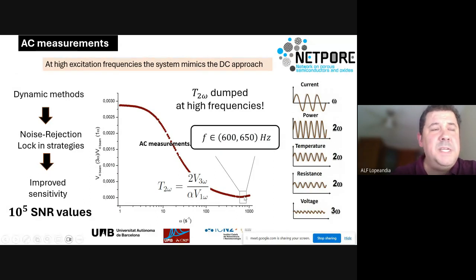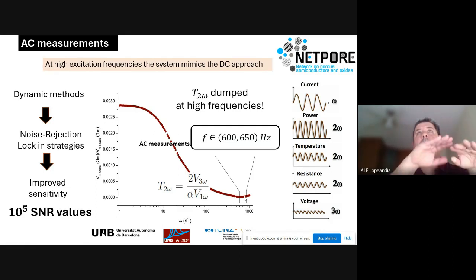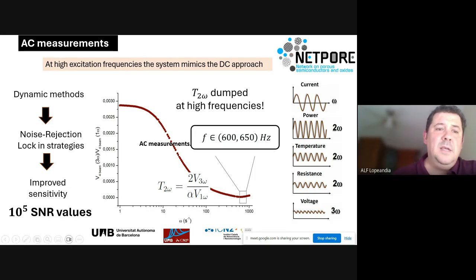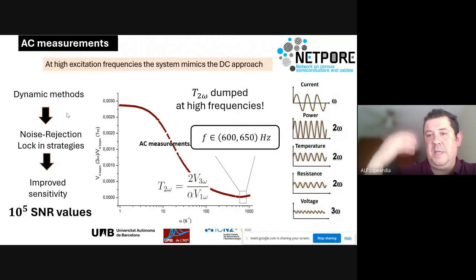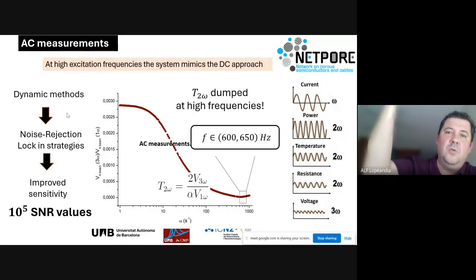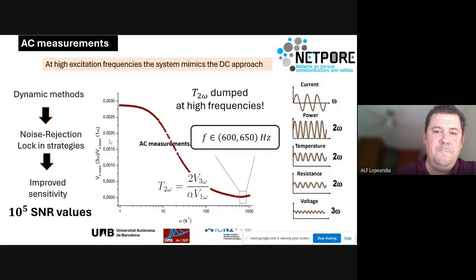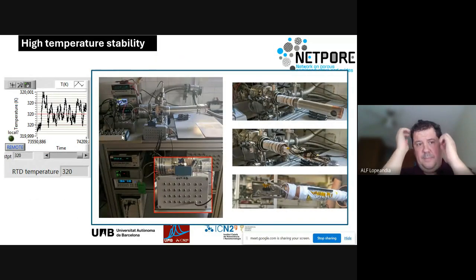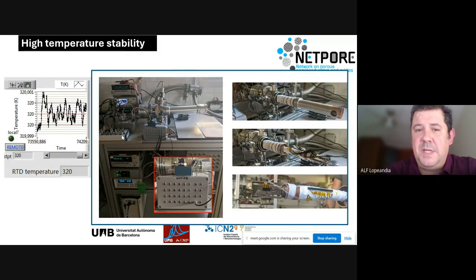It essentially means that our system electrically will have the AC component, but thermally we will behave as a DC system. Through that strategy, using those dynamic methods, we can highly reduce the noise, using noise rejection lock-in amplifier strategies. And we typically get signal to noise ratios, determining the resistance, of around 10 to the 5. 10 to the 5 means that the magnitude over the uncertainty is around 10 to the 5. Of course, if you have that type of sensitivity, you also require a system with similar sensitivity.